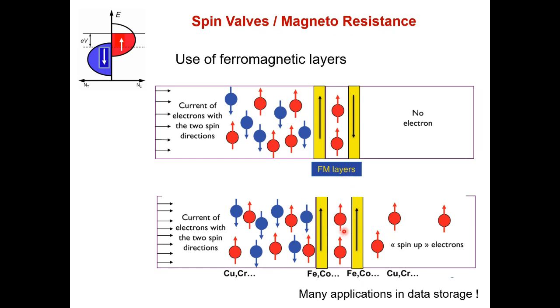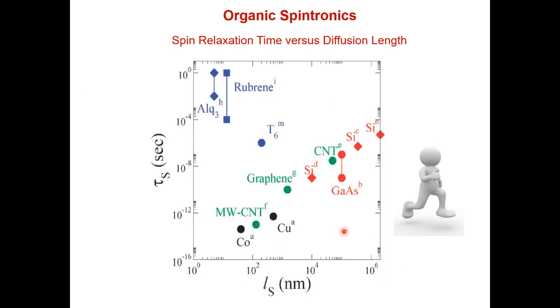So this is what you will see in my last slide. Typically, there are two key parameters: the spin relaxation time, how fast the spin goes in the opposite direction, which is very bad for the device, and how far the charge can go before the spin is flipped. And you see that all the inorganic materials are very good to give rise to long diffusion length, but they have a very, very short spin relaxation time.